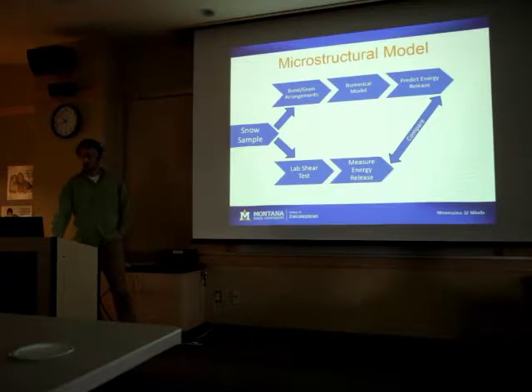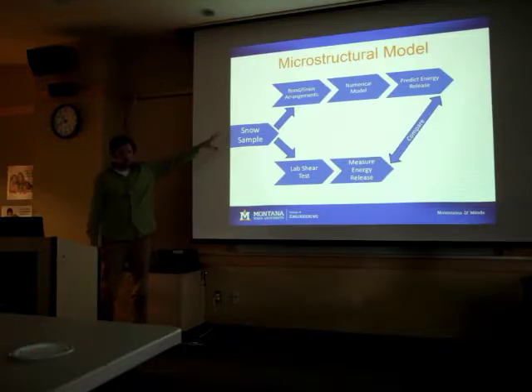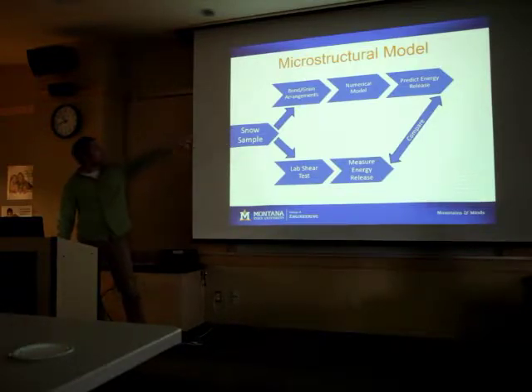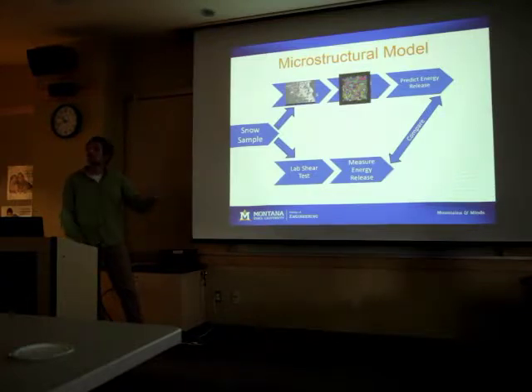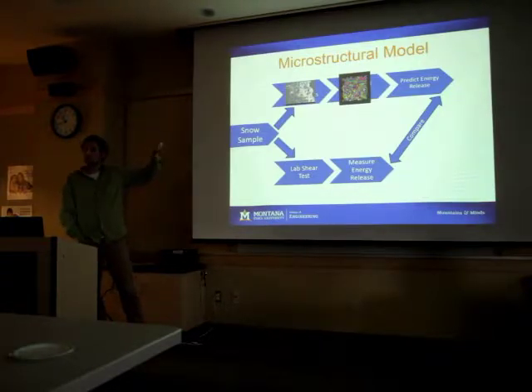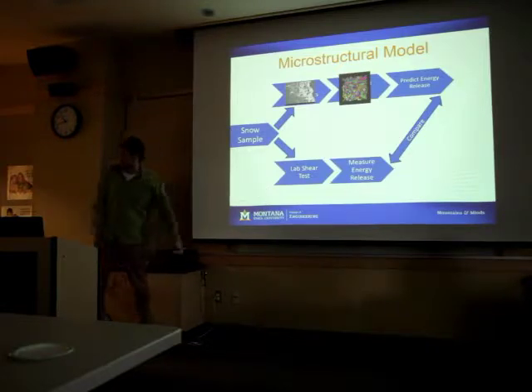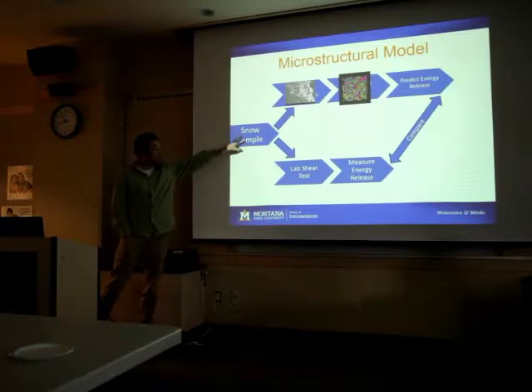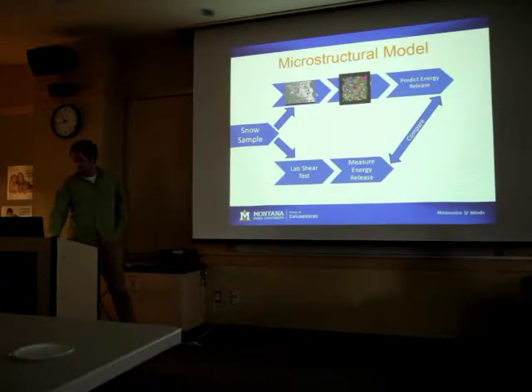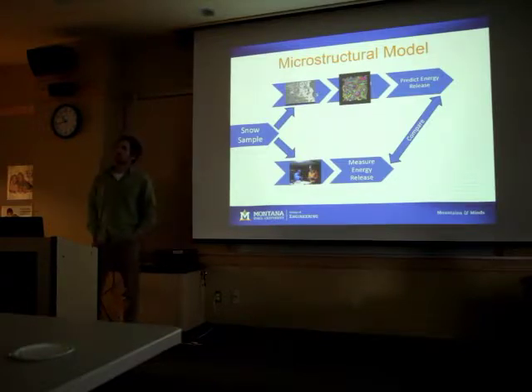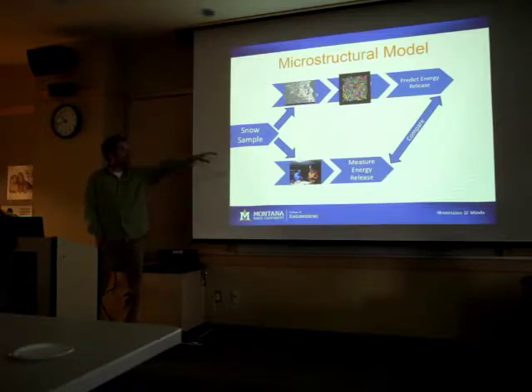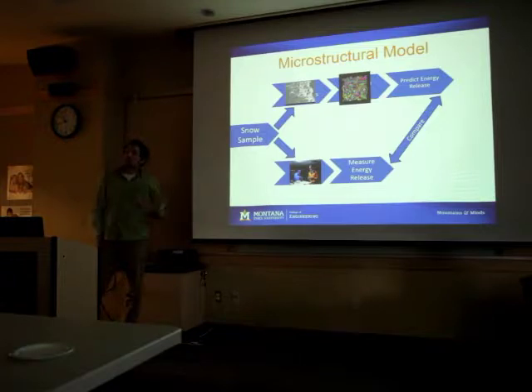Here's an overview of how the modeling process works. I start with a snow sample, put it in the CT scanner, look at how the bonds and grains are arranged, and run it through a numerical model. The model tells me how much energy gets dissipated when that sample of snow fails. I also take a chunk from the same sample, do a shear test on it in the lab, and measure how much energy is released. Then I compare the results from the model with the results from the laboratory, and generally they agree pretty well.